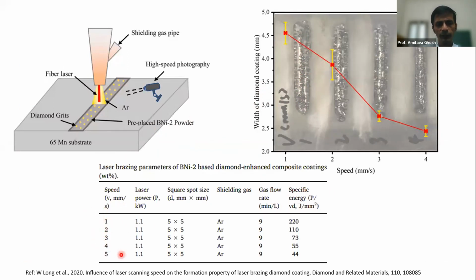So the scanning speed also matters a lot, because depending on the scanning speed, the specific energy changes. That means the energy concentrated on a particular area changes. And when we increase the speed, we have seen that if it is very low, it is detrimental. This has been done by W. Long in 2020, a quite recent paper. They have seen that if the speed is in the tune of 3 to 4 millimeter per second, that is good for the quality of the diamond brazing.